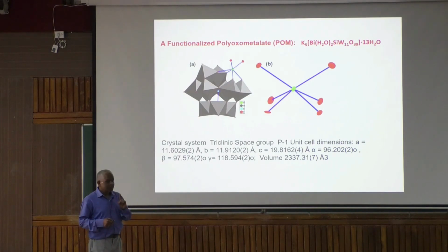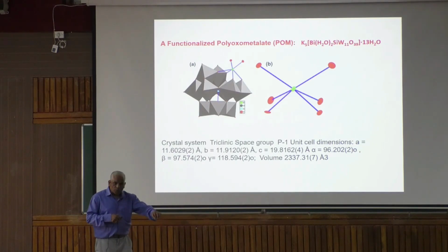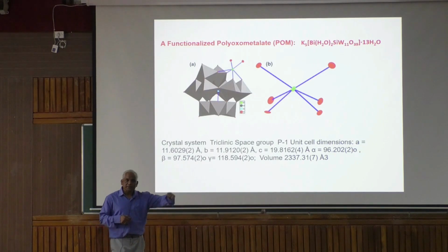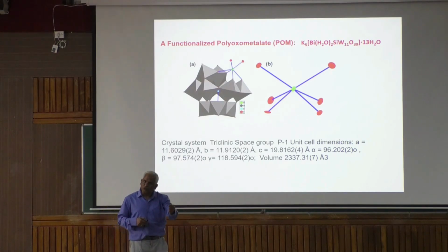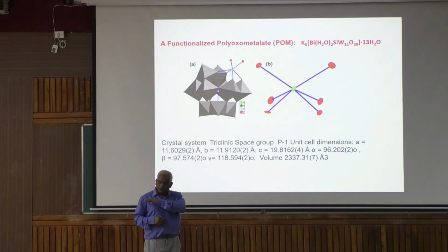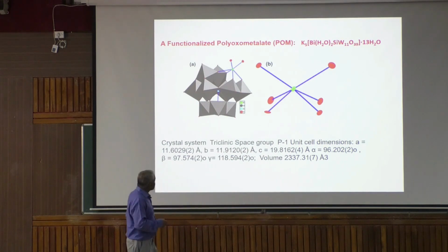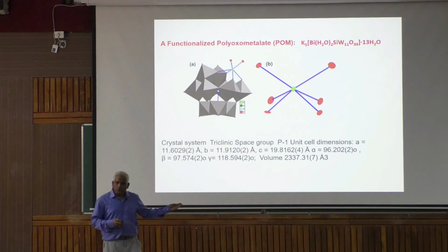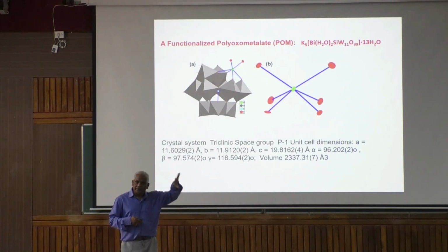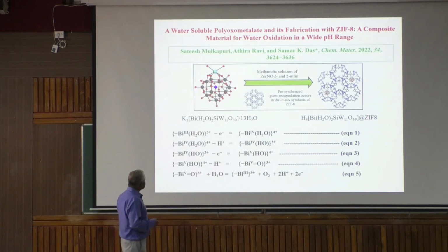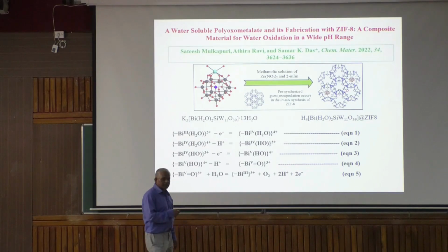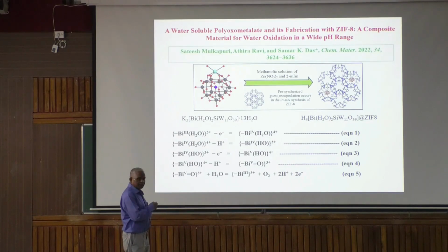But the problem is, this compound is highly water soluble, first of all, and this particular compound, when you put it in water at neutral pH, slowly decomposes. Because polyoxometalate, I already told you, at alkaline pH decomposes immediately, instantaneously. At neutral pH also sometimes it slowly goes. But with this compound, this is a problem. This is what we thought. Earlier we thought you can encapsulate this compound in the same MOF. So what we did, we took the same MOF, ZIF, because these fit in size nicely.